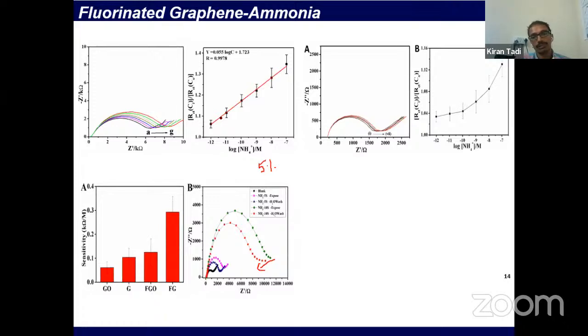So we thought that if we increase the doping level, it may increase the sensitivity more and more. So that's what we did here - we increased the levels to 20% of the fluorine, but in this case the sensitivity reduced a lot.